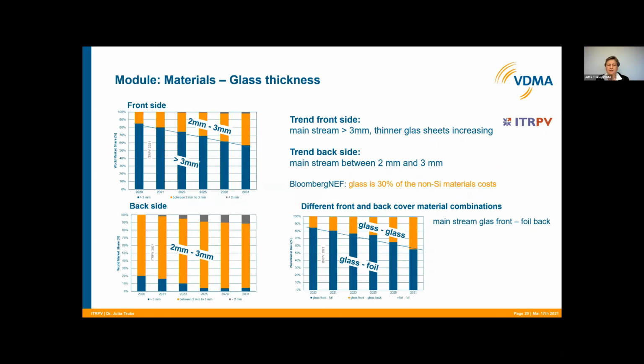The other big part of costs in the module is the glass, of course. Last time BNF showed that about 30% of the non-silicon materials costs in the modules come from the glass. At the moment, the glass on the front side is still bigger than 3 millimeters, but the smaller ones, between 2 and 3 millimeters, will come up. On the back side, it's mostly already the thinner one between 2 and 3 millimeters. But bifacial modules are mostly glass-glass, and this is a part which will come up in the future, as you can see at the lower right part. But the glass-foil is at the moment still 80% market share.